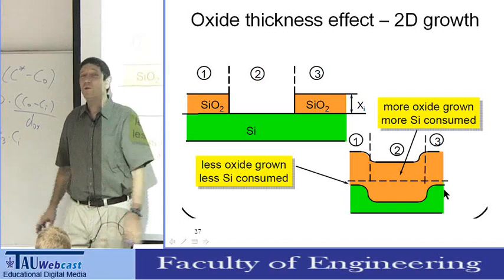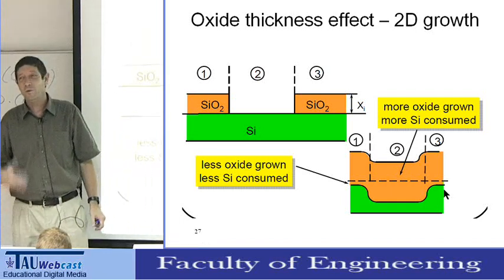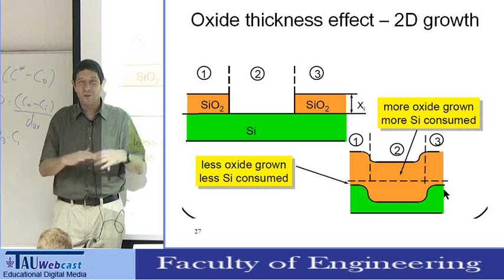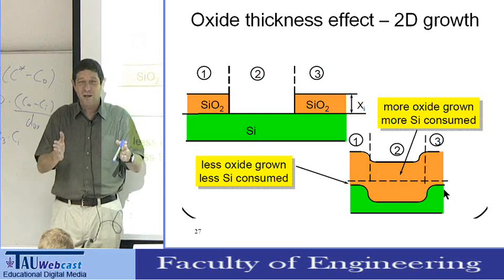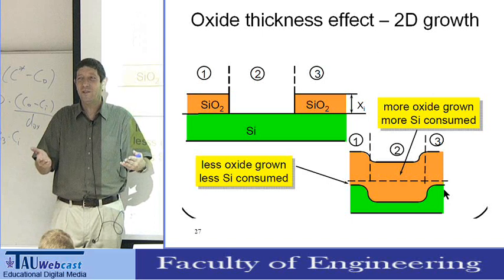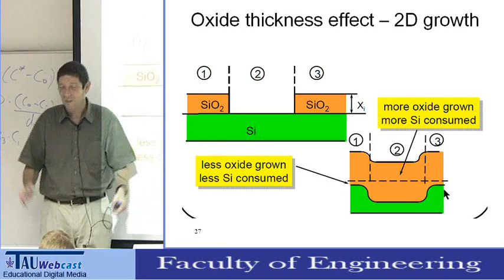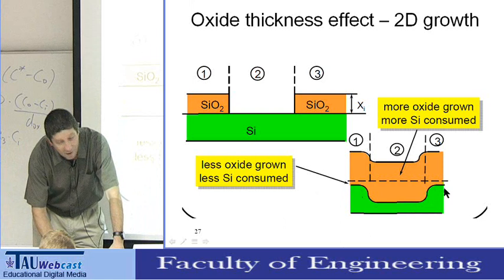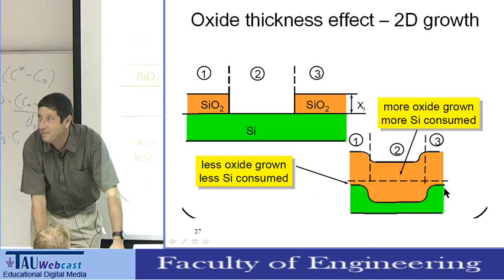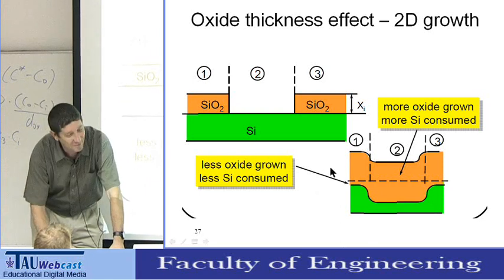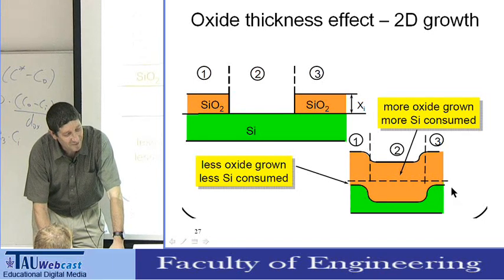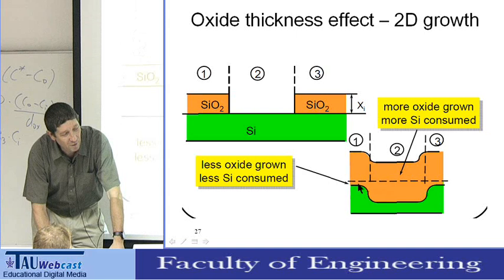And this is, by the way, an old trick: if you want to mark your silicon and you don't want to etch it, you grow an oxide, you etch what you like, you oxidize again, and then remove the oxide. And you end up with this green interface. And this was in the exam last year, to guess the shape here and to give the value here.